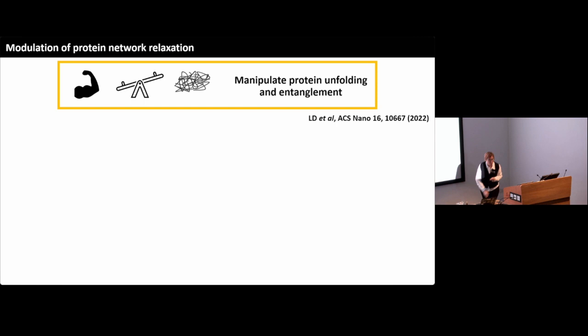The other thing that we can start to play with is the mechanical robustness of the protein. So if we have something which is mechanically strong and unlikely to unfold, then we will have a network that assembles a little bit like a colloidal-based system where we have patchy colloids going through an aggregation process. If we allow more of that unfolding to occur, then we have these biopolymers, which are elongated in the solution. And in some cases, we can do that so it's favorable for them to entangle. And now polymer entanglement is the thing that can dominate our system. So I think it's really interesting. Thinking about the theory of these systems is quite interesting and challenging, because it straddles the colloid-based literature and the polymer physics-based literature, which is, of course, extremely rich, but we need to think about how our system can learn from each of those fields, and that's something we're enjoying.